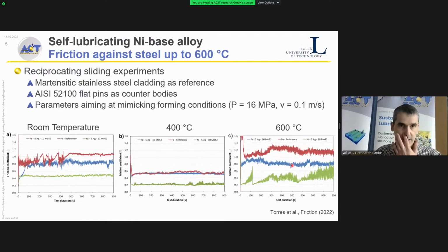So we check this nickel self-lubricating alloy under different conditions. The first one is, for example, reciprocating sliding mode experiments against martensitic stainless steel. We always use some material as a reference. In this case, we use also martensitic stainless steel cladding as a reference, this is the red line. And we can see here that when we use the martensitic stainless steel, friction is very high. And when we use, for example, the nickel-based alloy, the green lines, we are able to have a very steady and low friction.